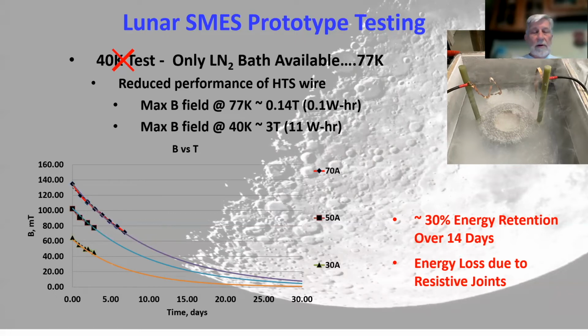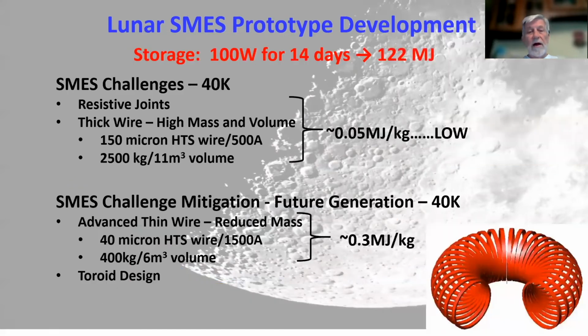However, if you see from the graph on the left, energy storage was done at a number of levels of current injected into the coil. At the 70 amp current injection, we see that at 14 days, we have about 30% of energy that had been retained in the coil. The rest was lost in the coil due to the resistive joints in the coil. And that is a challenge that has to be mitigated in follow-up designs.